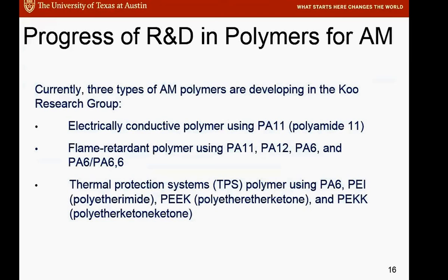And there's another area we spend a lot of time on, flame retardant polymer for nylon 11, 12, 6, and 66. We spend a lot of time in there, and they are similar, but there are differences. And it's not like one formulation works for all nylon. It doesn't. Okay. And another area now we're starting to look at is called thermal protection system (TPS). And we first started with nylon 6, and now we're moving to PEI, and we are getting materials from Evonik, PEEK, and we are getting materials from Arkema, PEKK. Okay, those are the ones that we're now moving towards, mostly for TPS application.